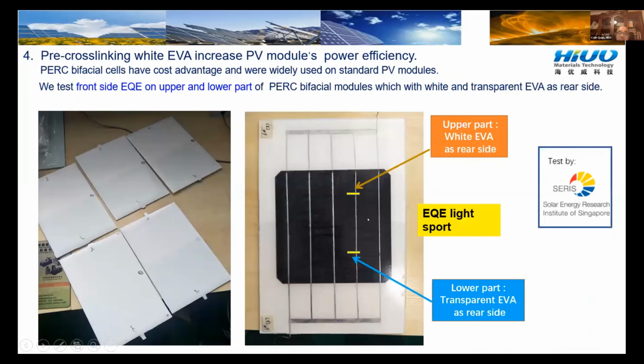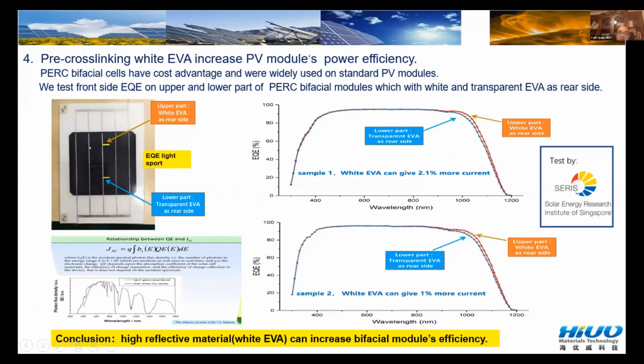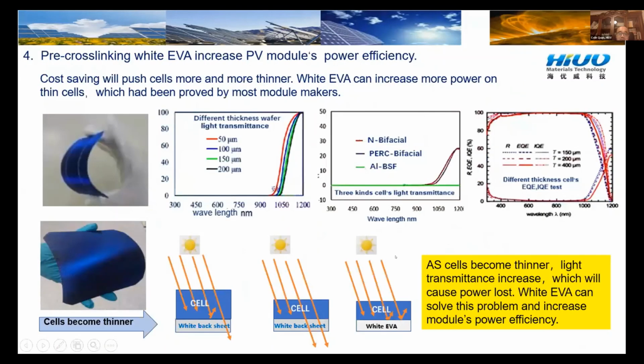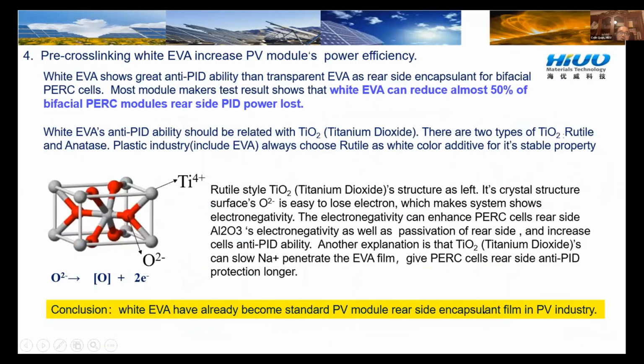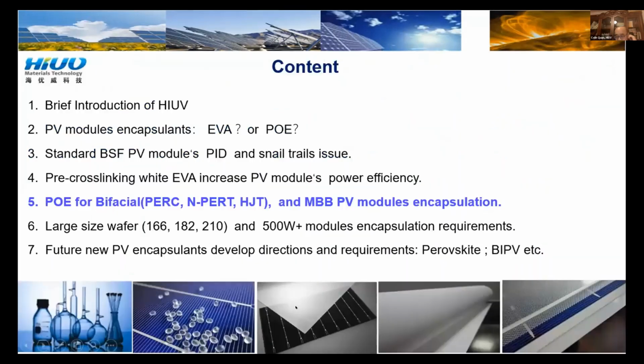So we did some EQE tests. Comparing that part with the white EVA on the back, we got a 2.1% current increase. This was tested by SERIS. So as cells turn thinner, it will generate more power. Also, the white EVA with titanium dioxide has some positive phenomena in the system, which can increase the passivation of the Al2O3. That is the reason why it can increase the module's anti-PID ability for white EVA.